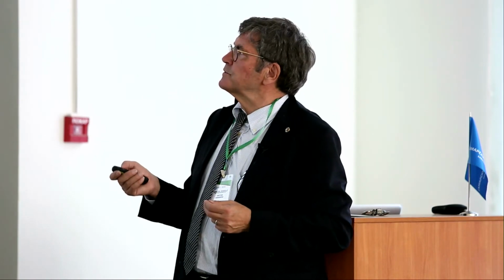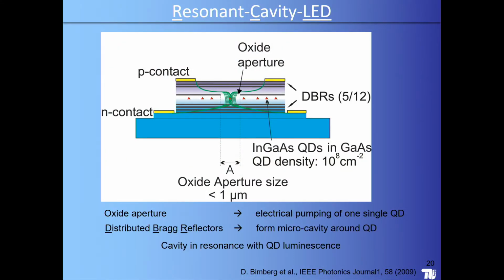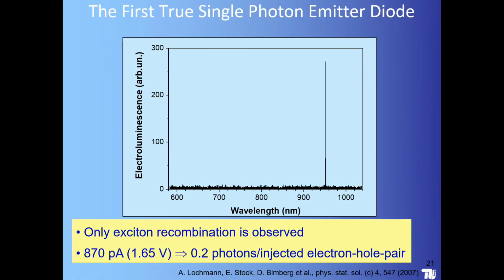Next was the resonant cavity LED. We just introduced DBRs here, 2 stacks of DBRs. And now we have quantum dots in a gallium arsenide cavity, density of 10 to the 8 per square centimeter. And if you're lucky, you have a quantum dot below this aperture. And we can then pump electrically one single quantum dot. It's a PIN junction, very simple. You have here the P contact, here is the N contact, yeah? And we have a micro cavity, and the cavity must be, of course, in resonance with the luminescence, but all that can be done.